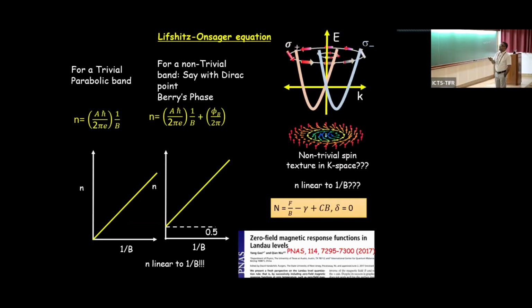But recently a paper came which says if you have a non-trivial spin texture in k-space, which Rashba might provide, then this Lifshitz-Onsager equation is now modified by a term which is C times B. This C is a derivative of susceptibility, right? Derivative of susceptibility. And then if you plot this, this should not be linear in 1 over B.